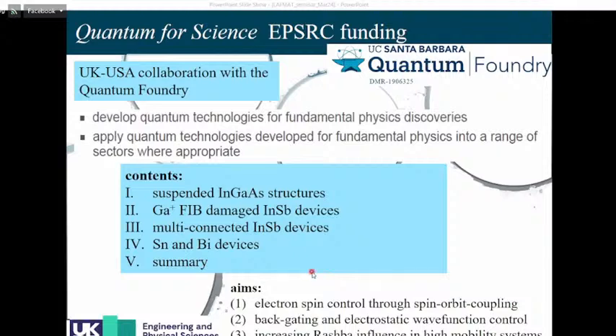The overall aims of these projects are controlling the electron spin through spin-orbit coupling, and applying electric fields to move the wave function in the crystal, so-called gating. Also increasing the spin-orbit coupling effect called the Rashba effect. The Rashba effect is a spin-orbit coupling effect that can happen when you have interfaces and asymmetric potentials caused by doping or heterostructures, particularly in high mobility systems. A lot of these material systems are quite low mobility. We're hoping to push the mobilities up into cleaner systems, but still be able to control the spin-orbit coupling effect.